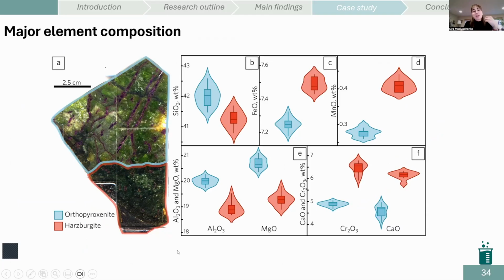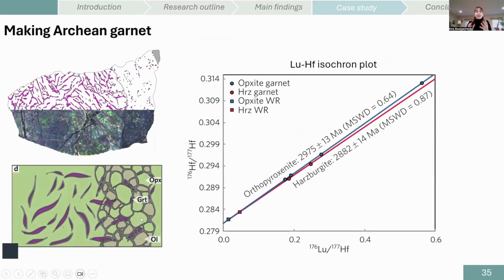So it raises the question: what actually happened with a sample like that? Honestly, having a sample like that with garnet on both sides of it and a really peculiar texture on one side gives an excellent opportunity to test the limits of our new method of lutetium-hafnium geochronology. Similar rocks have been described previously in the literature from the Kaapvaal Craton and from the Tanzania Craton, but none have been dated with this method, and certainly not at the scale required to isolate different textural domains. The analytical challenge here was the extreme depletion in both lutetium and hafnium on both sides of the sample, which made me process almost the entirety of those precious parts to get the age, and we pushed the method all the way to the detection limits.